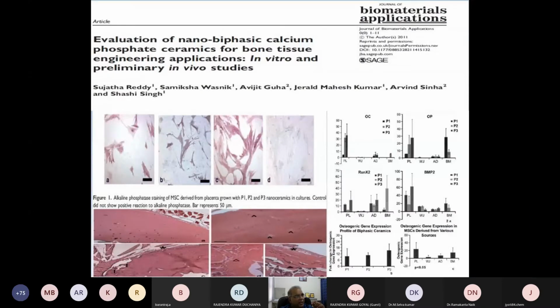CCMB carried out in vitro and in vivo experiments, meaning experiments with the cells in the petri dish as well as experiments using animals, and they found that this two-phase material developed by us in a biomimetic way, when it is exposed to stem cells, within a short time starts converting to bone-forming cells. And this paper has been published.